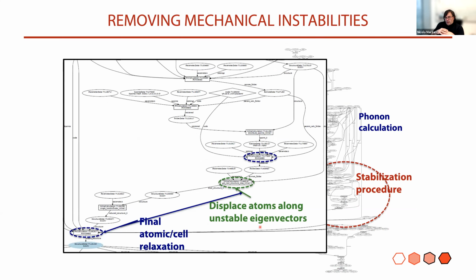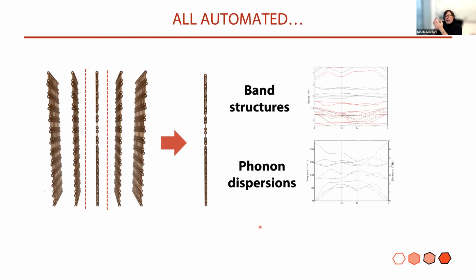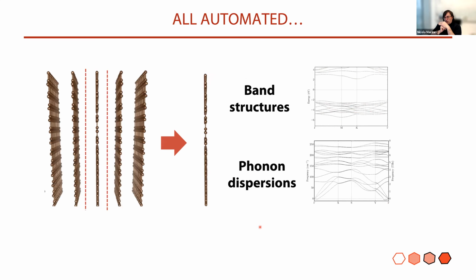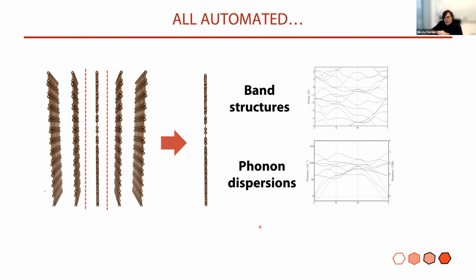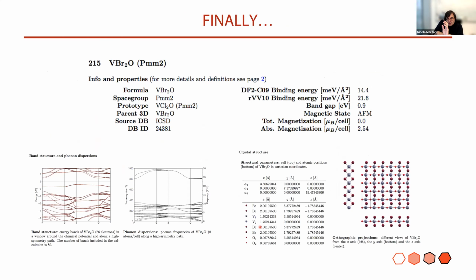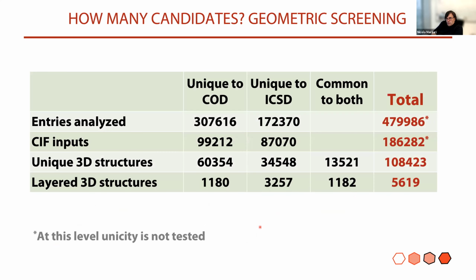Is the stress zero? Are there any soft modes in the phonons, in the normal modes? And as I said, we want to do this in an automated fashion, in high throughput, in robust and reliable ways. And this is done day in and day out. It goes into our human readable form, into our curated database, where here exactly this is the result of a calculation. For this vanadium bromine oxide, you see what we have calculated in terms of being exfoliable, very low binding energies, an antiferromagnet with this band structure, this phonon dispersion, these cell structures, and with all the properties that we are looking for.